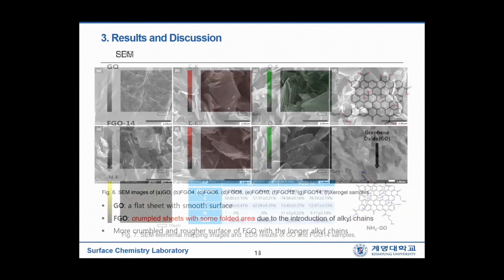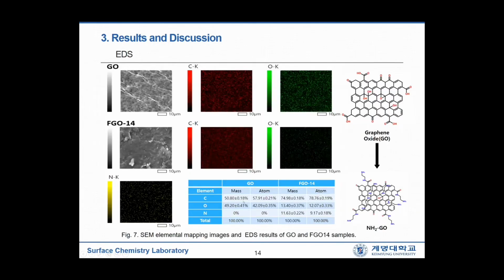These are the elemental mapping images and EDS results of graphene oxide and FGO14 samples. As you can see in these images, we observed carbon, oxygen, and nitrogen in the aminized graphene oxide. These are TEM images taken for the samples of FGO4, FGO14, and IF-WS2. We can see a piled-up layer structure of inorganic fullerene-like WS2, like an onion.